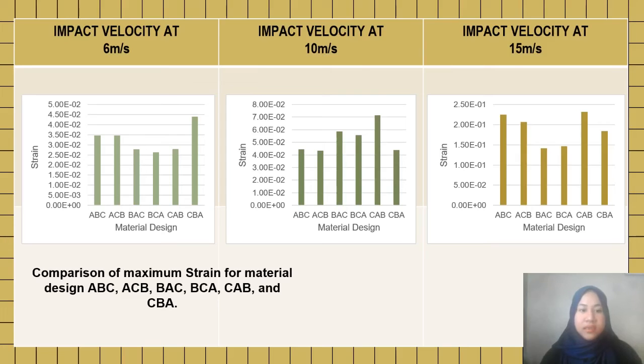And now, this is the comparison of maximum strain for material designs ABC, ACB, BAC, BCA, CAB, and CBA. From the graph, the maximum value of strain at impact velocity 6 meters per second occurs on material design CBA, and it is different for impact velocities 10 meters per second and 15 meters per second, where the highest strain occurs on material design CAB, which are 7.157 × 10^-2 and 2.317 × 10^-1 respectively.